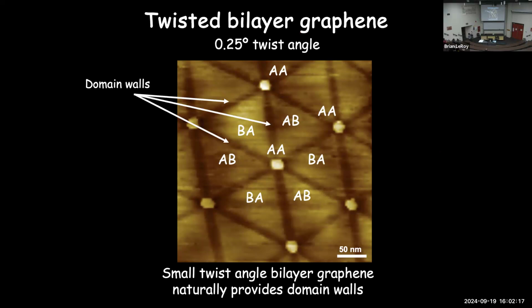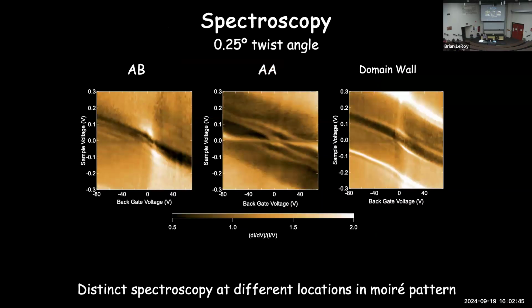These bright spots are where we have AA stacking. And then we have AB and BA stacking alternating going around them. And there is some kind of domain wall separating the different stacking configurations. So what we're interested in is probing the electronic properties of this structure at the different symmetry sites here. So this AA site, this domain wall, this AB sites, etc. And so that's what's shown here. So the color scale is the density of states. Bright means high density of states. Dark means zero density of states, or in the middle of a gap.